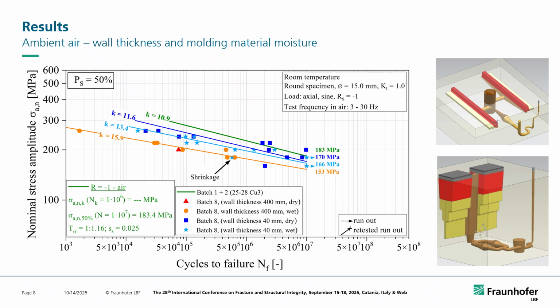Coming to the wall thickness influence, comparing the results from this 50 millimeter block and those specimens that we have with a graded or stepped wall thickness, it was really interesting that we had, at the end, a worse result from the fatigue point of view until 10 to the power 7 cycles when we go from 50 millimeter to those 40 millimeter specimens. Usually we say when the wall thickness is smaller, then we have a better microstructure due to a higher cooling rate, and we get a better fatigue strength.